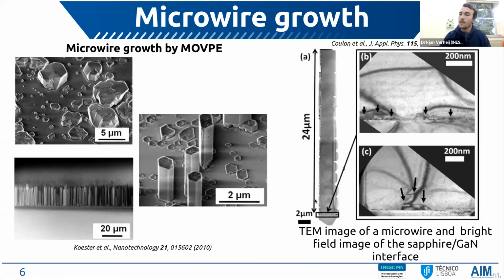This does not mean that the mismatch between the sapphire and the gallium nitride entirely disappears. It still exists. Because if we zoom in at the bottom part here, where the sapphire-GaN interface is located, we can see that the mismatch still exists, as shown by the black arrows here, but that the dislocations are bent towards the side wall of the microwire because of the specific 3D nature of the structure. So they are relaxed and bent towards the side wall of the wire, very close to the surface or to the substrate. And the rest of the wire, like I said, is kept essentially dislocation free.